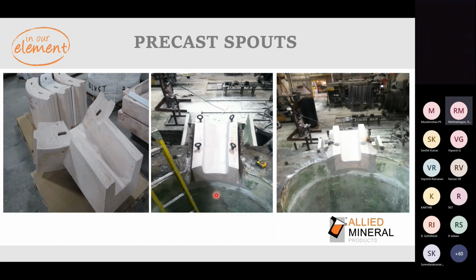So the way to install is actually you put a plastic refractory in the bottom where I'm showing with the cursor, and then you set the precast tap hole, precast spout, and then on the side again you can fill it with the plastics to hold the spout in place.